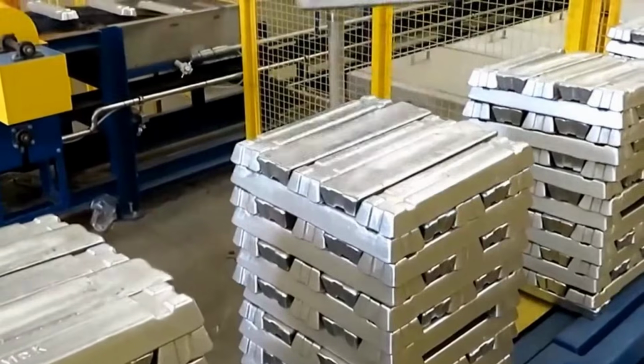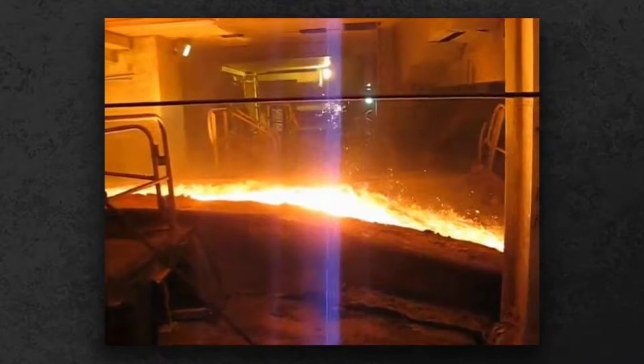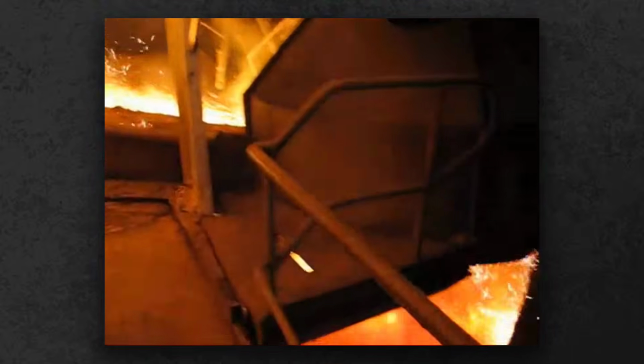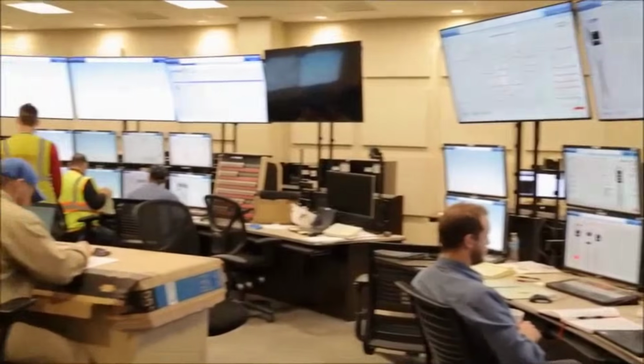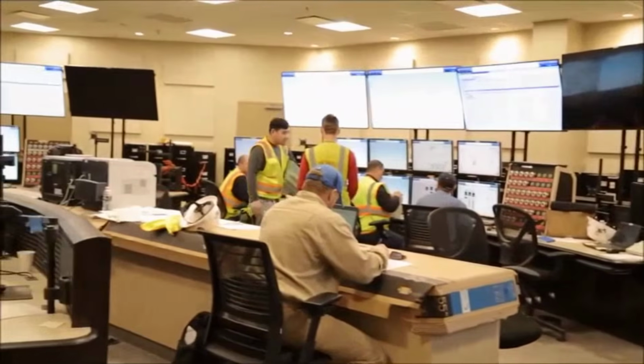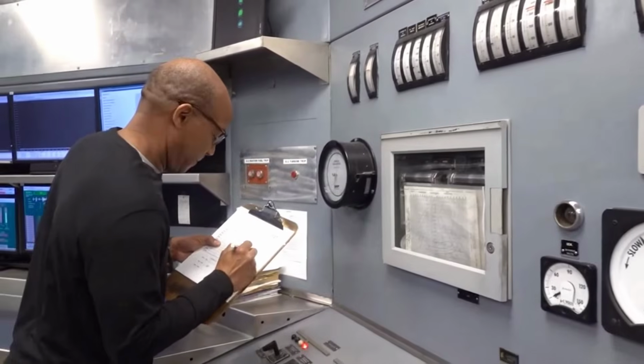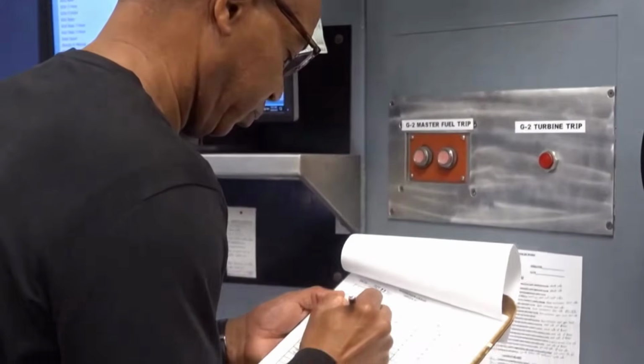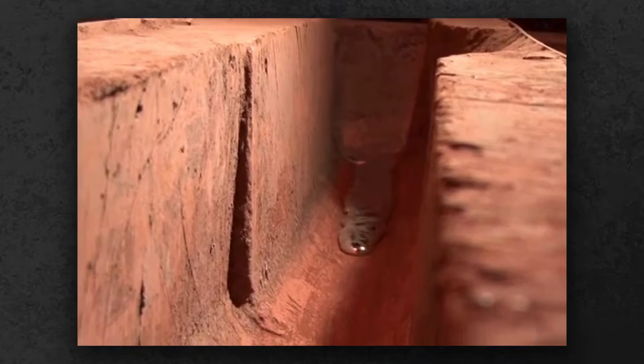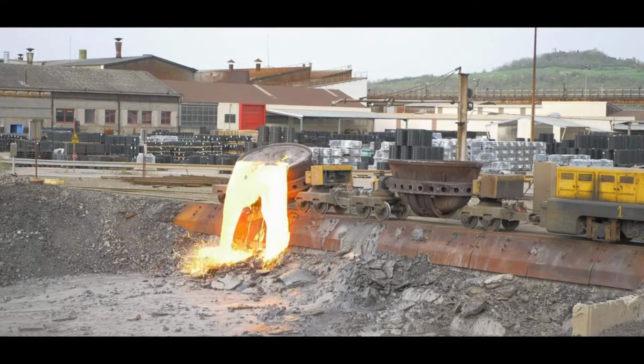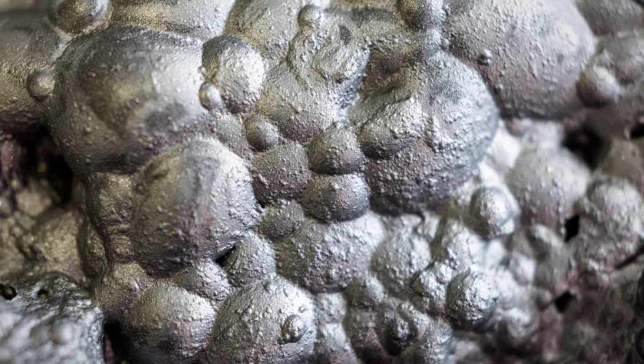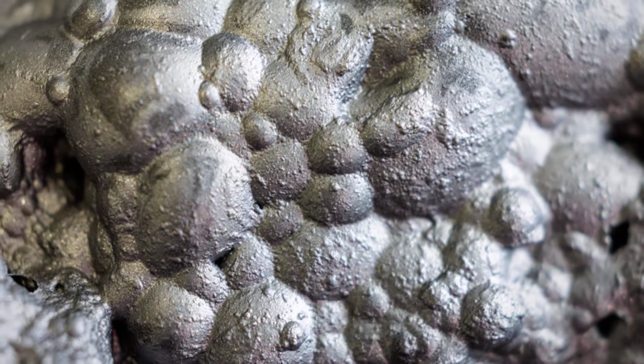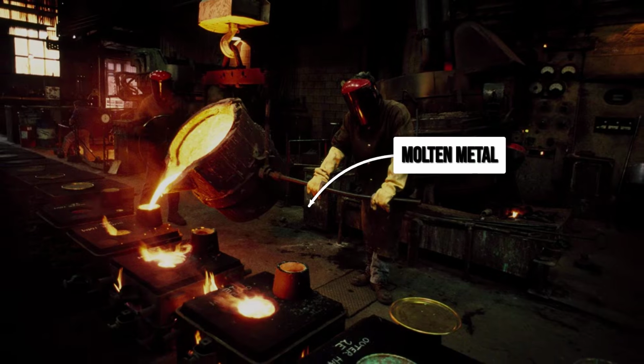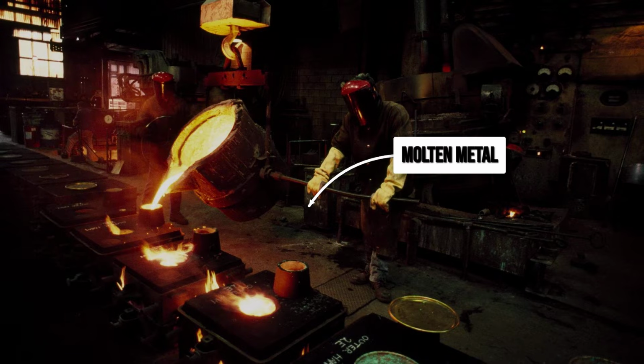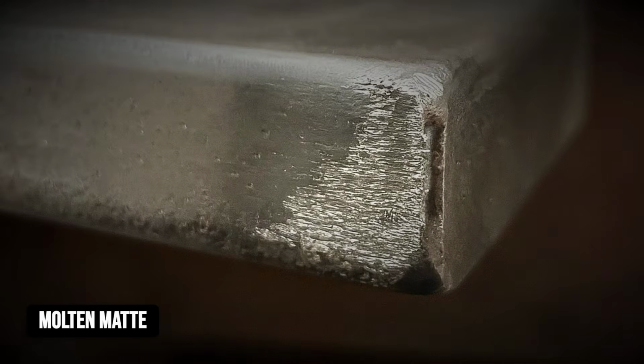Silica fluxes blend with the molten mass, coaxing iron and unwanted elements into a glowing river of slag that floats to the surface. Technicians monitor the color and flow, ready to adjust power or flux if readings stray from target. Every few hours, a tap hole is opened. Molten slag spills away, leaving behind a dense metallic layer called matte. This matte holds platinum, palladium, and other platinum group metals, now separated from most impurities, but still far from pure.